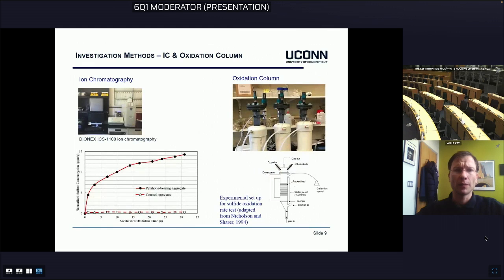Next slide, please. On the left side, you see a result from ion chromatography we have run on pyrrhotite-containing aggregates, where the surface has already shown some indication of pyrrhotite oxidation, and the graph below shows the release of sulfates, which is a reaction product when the pyrrhotite oxidizes into the solution, and you can measure this over time. The solution is, for example, hydrogen peroxide, which accelerates oxidation, in comparison to control aggregate, which does not have any pyrrhotites at the surface which could react. And you see the dotted line is flat. So this is a method to indicate the reaction rate.